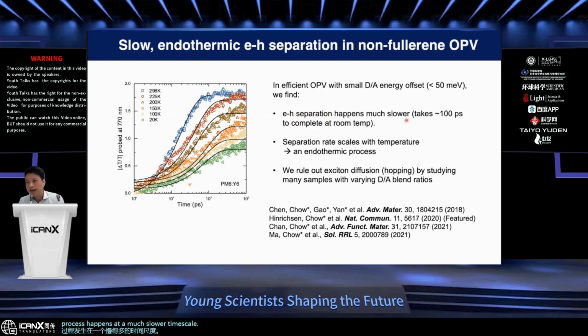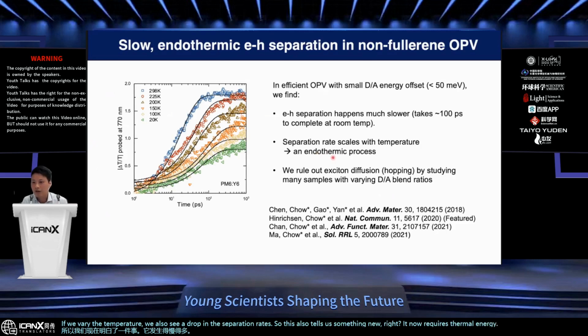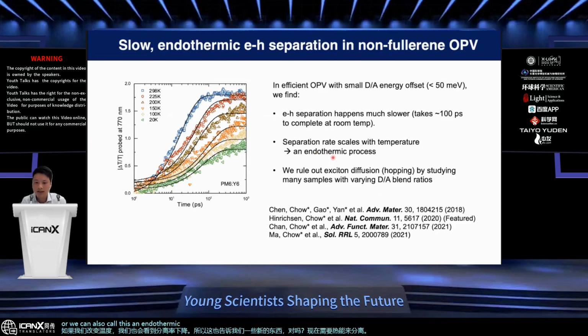Before it was like 100 femtoseconds, but now we actually see this to be almost 1,000 times slower. In fact, it takes all the way up to 100 picoseconds to fully complete. So we now understand one thing: it happens a lot slower. If we vary the temperature, we also see a drop in the separation rate. So this also tells us something new: it now requires thermal energy in order to separate, or we can also call this an endothermic process.